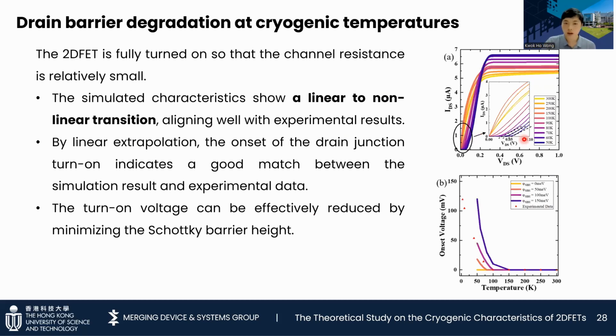Based on the new understanding of the carrier conduction mechanisms, we simulate the IV characteristic of the 2D FETs. Here, we assume that the 2D FET is fully turned on, so that the channel resistance is relatively small. Under this assumption, the channel behaves as a resistor, whose resistance reduces as the temperature is lowered. As shown in this graph, the simulated IV characteristic shows the linear-to-nonlinear transition, aligning well with the experimental results. Also, by linear extrapolation, the onset of the turn-on is shown in the bottom figures here, indicating a good match between the simulation results and the experimental data.